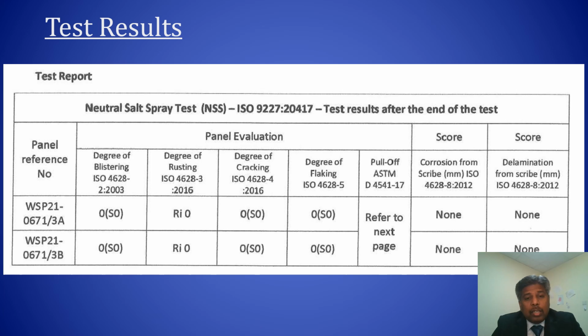The test results from the neutral salt spray testing are clearly tabulated here, and you can see that the coating system consisting of a zinc phosphate based epoxy primer applied at about 100 microns DFT, followed by a solvent based intumescent coating, with a thickness of around 500 to 600 microns, followed by a polyurethane top coat at 100 microns, was excellent in terms of corrosion protection, and you can see that very clearly in this slide. So the coating system was able to withstand the accelerated weathering process.